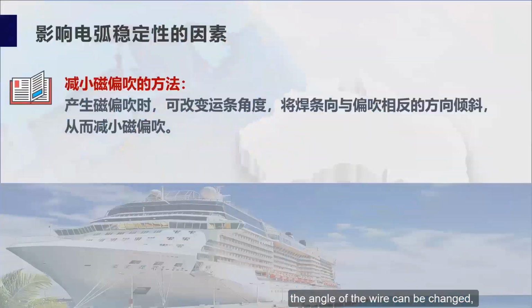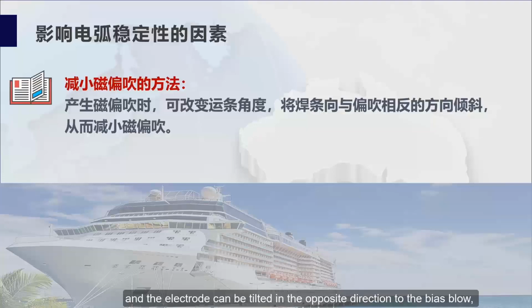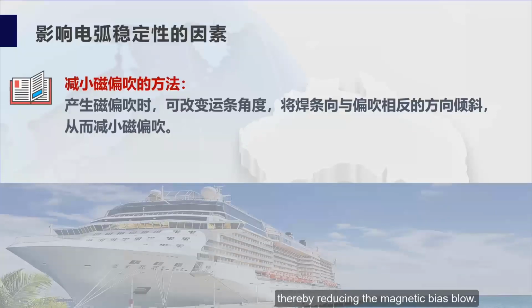When the magnetic bias blow is generated, the angle of the wire can be changed, and the electrode can be tilted in the opposite direction to the bias blow, thereby reducing the magnetic bias blow.